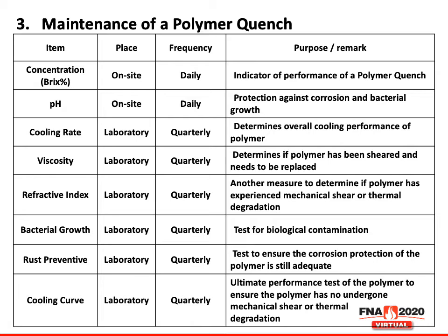Here's what's recommended to properly maintain a polymer quench. Concentration on site every single day. Should be done at least once a shift, at the start of every shift. pH. If you don't have a pH meter, something like litmus paper, and it's very inexpensive, can be used. Cooling rates, viscosity, refractive index, bacteria growth, rust preventative testing, cooling curves, those should all be done by your supplier.